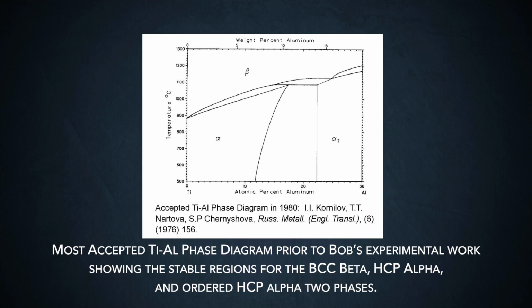But it also was found by people that at much higher aluminum contents, that is, contents still less than 50%, but greater than, say, 30% aluminum and titanium, the material would form an ordered hexagonal structure called the alpha 2 structure, with Ti3Al as the prototype. But how you went from the disordered alpha hexagonal phase at low aluminum contents to this ordered alpha 2 structure as you added aluminum was very debatable.